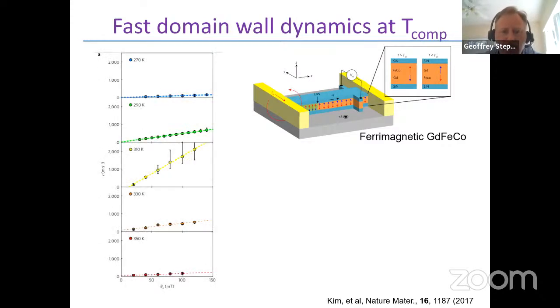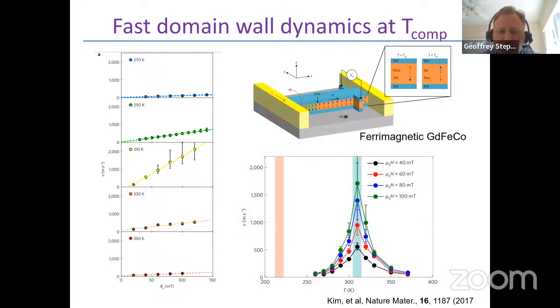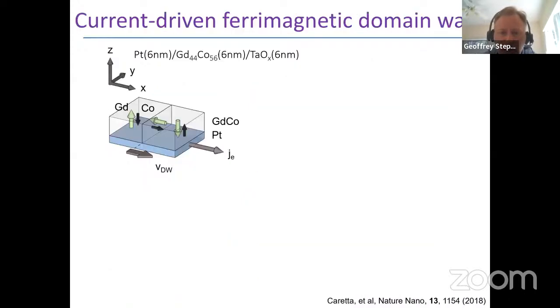And so it's been shown under driving field that magnetic domain walls away from compensation precess, which leads to a limiting velocity. As one goes towards compensation, in this case controlled by temperature, very fast velocities can be achieved, because the precessional motion that tends to limit that velocity, that critical velocity at which precession takes over, will tend to diverge towards the compensation point.